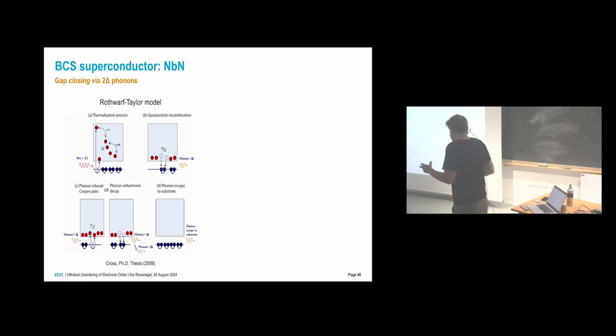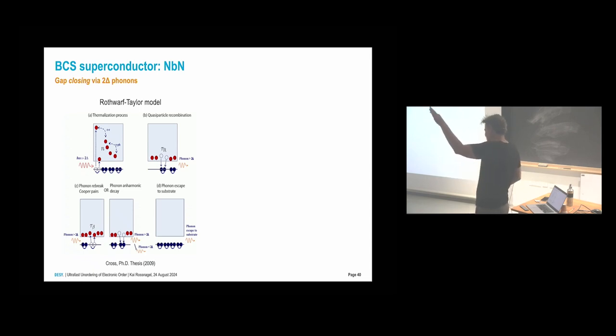There are the superconductors. In superconductors, you have to break the Cooper pairs to close the gap. You do the electronic excitation. The electrons have to transfer their energy to the 2 delta phonons, which break the Cooper pairs, and this then leads to the removal of the gap. Okay, this you already see. This is an indirect process. It takes probably longer than in a charge density wave.